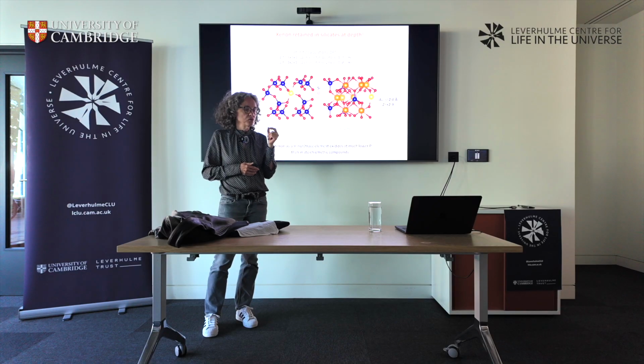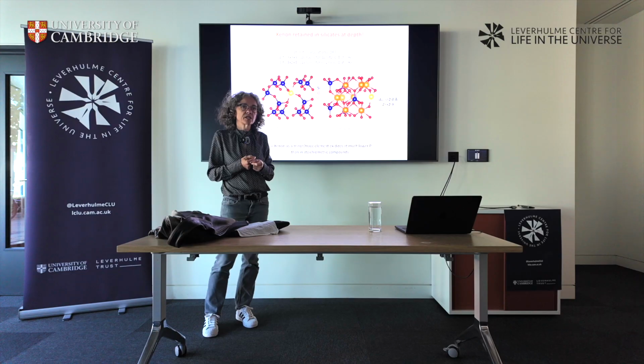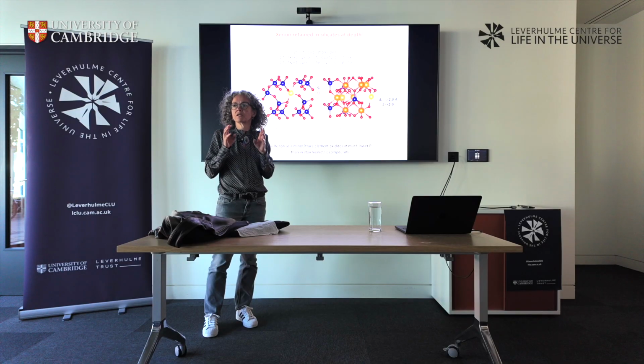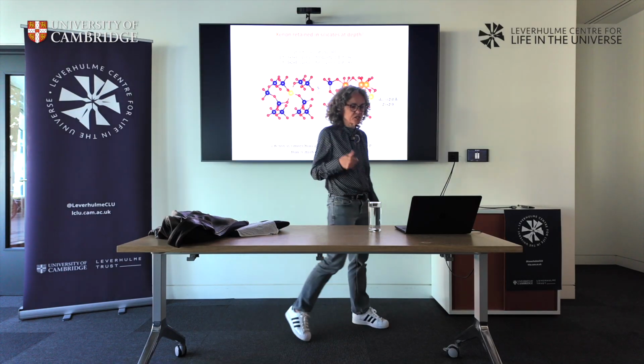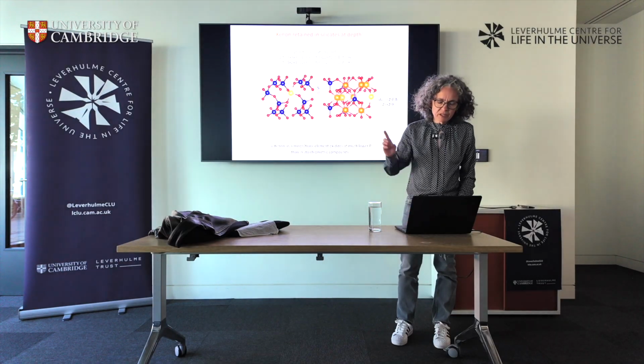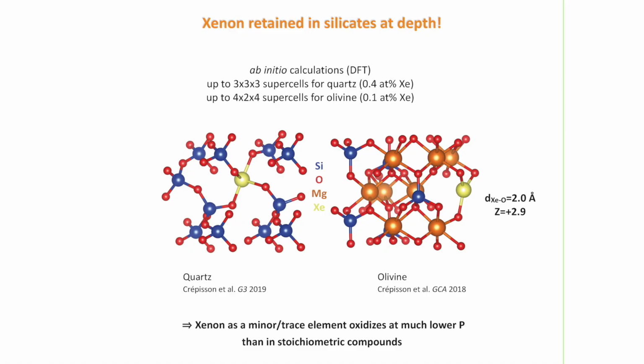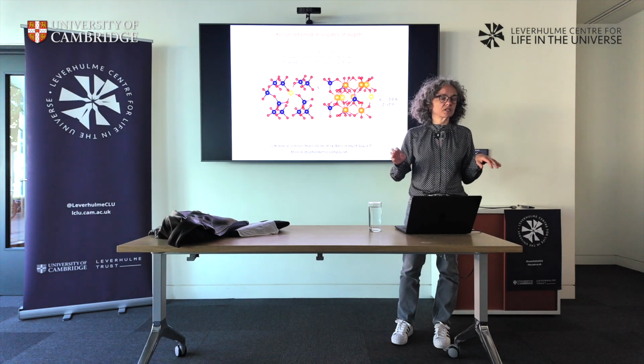So when you work with xenon as a trace element, somehow you have some chemical pressure, and you can have chemical xenon bonding occurring at much lower pressures than if you just start from pure xenon and pure oxygen. So you can induce this chemistry at much lower conditions. However, this happens at high pressure. If you release the pressure to room pressure, it goes off. The xenon is released from the structure.